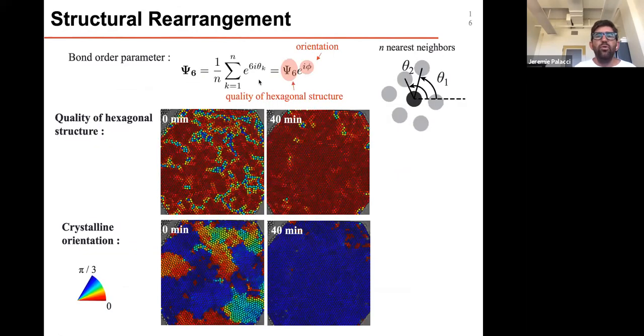And so to quantify the quality of our crystal, we look at the bond order parameter. Locally, if you look at the amplitude of the bond order parameter, you see that you have a good crystalline hexagonal order. But at the grain boundary, you don't have that quality. On the other hand, if you look at the orientation, you can clearly see the different orientations of the crystallites. So in our experiment, we start from many different orientations of crystals that convert after 40 minutes into one large crystal.